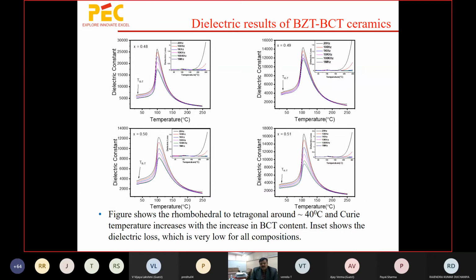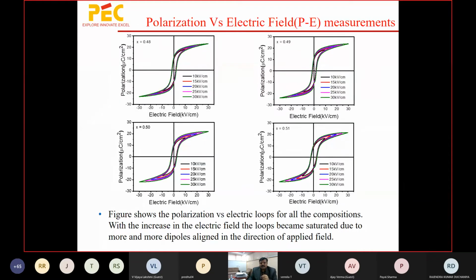What we observed is that at 40 degrees C for all compositions, there is a change in the structure. There is a very small anomaly that is shown by an arrow. That is the change from rhombohedral to tetragonal, right? And this plays a very important role in these crystals: the structural heterogeneity, to get the MPB, the morphotropic phase boundary, which is the combination of different phases.